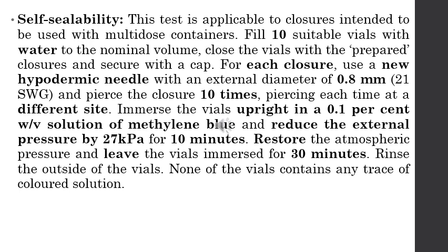Then reduce the pressure by 27 kilopascals for 10 minutes. After 10 minutes, restore the pressure and keep the vials as it is for 30 minutes.